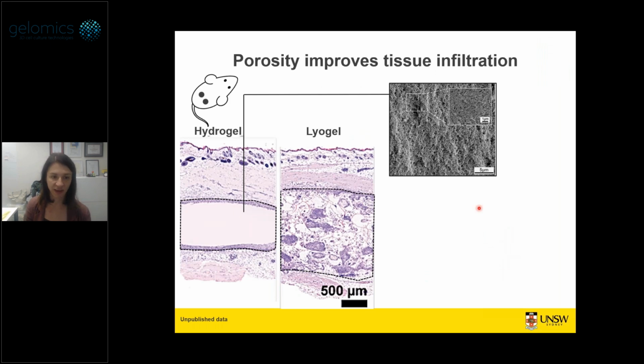And then there is the obvious advantage of the porosity that you've introduced, where your hydrogels have nanoporosity. So when we implant them in vivo in mice, so this is under the mouse skin here, you can see a little bit of tissue growth, probably fibrous encapsulation around the periphery of these, but there is very little to no tissue growth into the actual hydrogel because it takes a long time for the enzymes to degrade silk and actually grow in there. Whereas with the lyogel, we're getting really good tissue ingrowth into these materials.